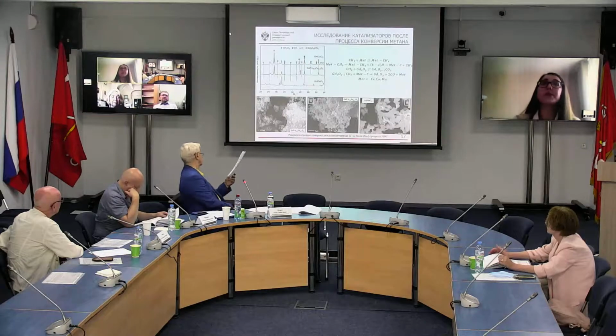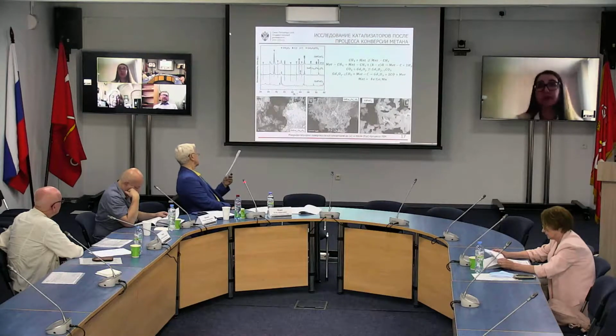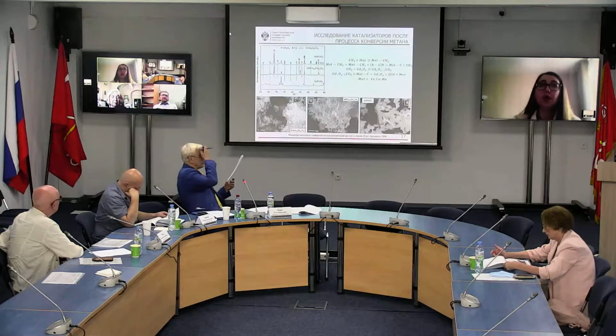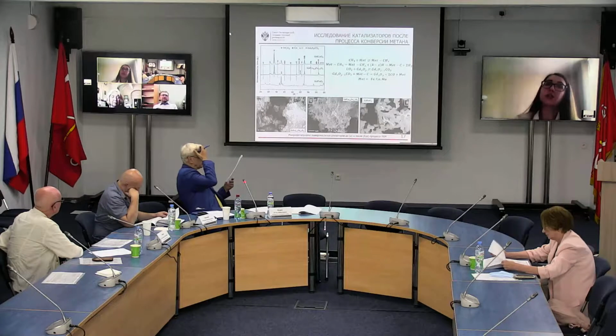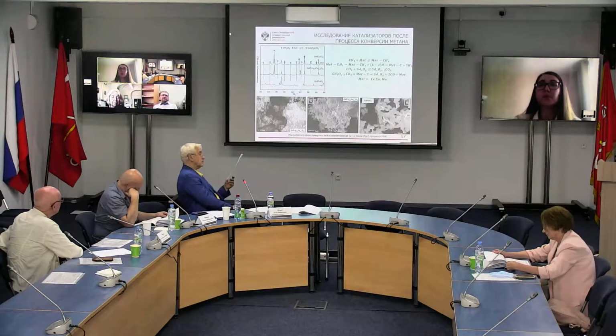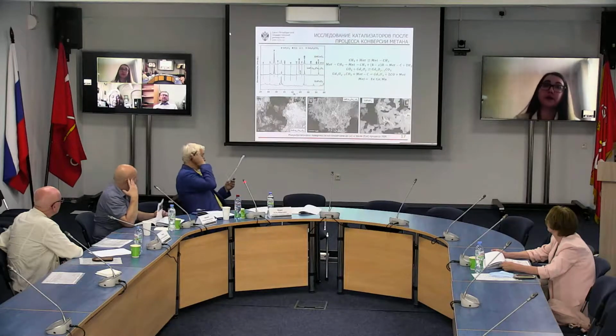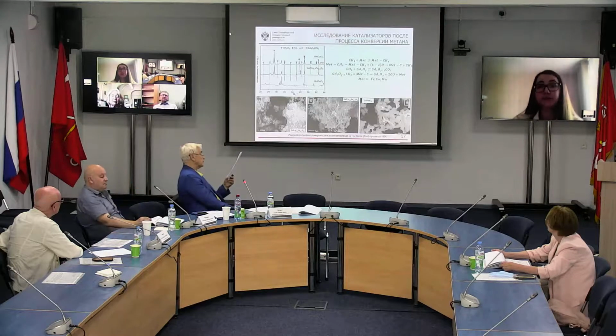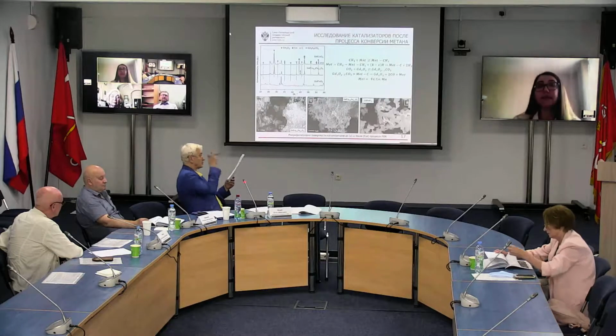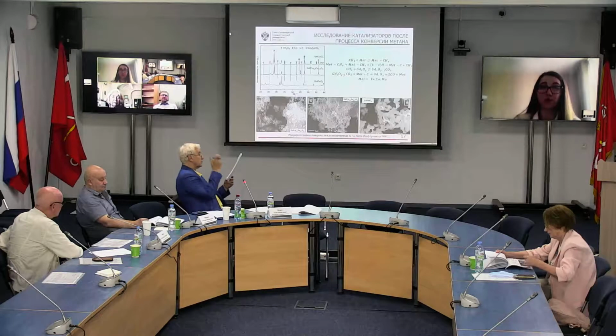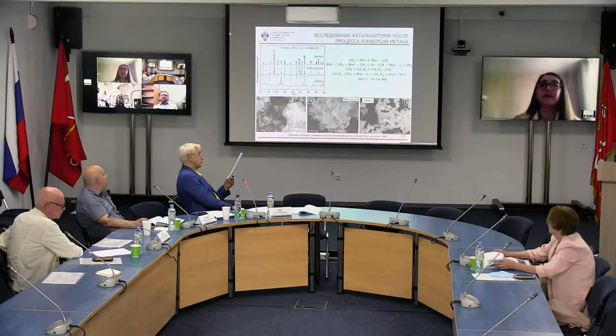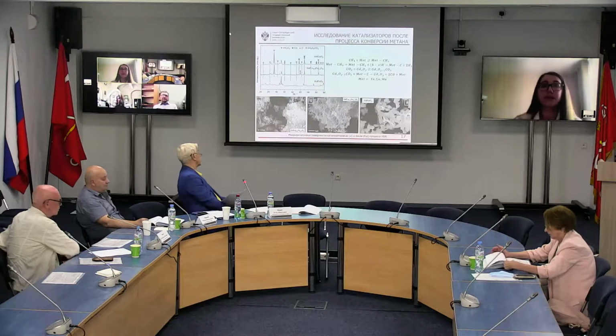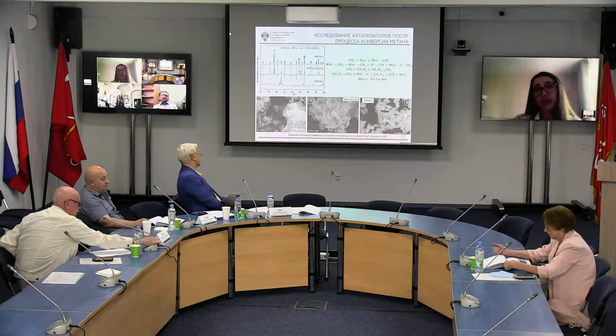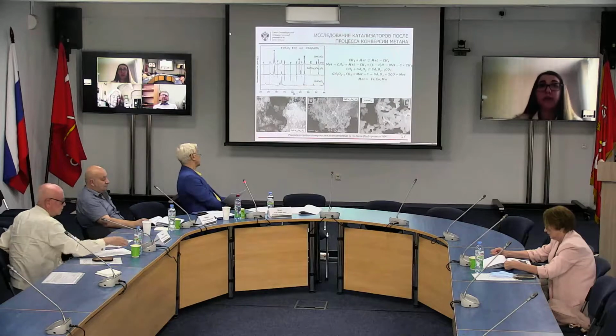The results are supported by the results of kinetic studies, and they confirm the mechanism of the process, according to which the process of dry reforming of methane forms intermediate carbonate complexes, and then we have reduction with radicals C, CH, and hydrogen. We have the formation of atomic hydrogen here and CH radicals. In such a way, the chemisorption processes happen on centers of different nature. The formation of surface carbonates happens on gadolinium atoms, and the formation of atomic hydrogen and CH radicals happens on iron, cobalt, and manganese atoms.